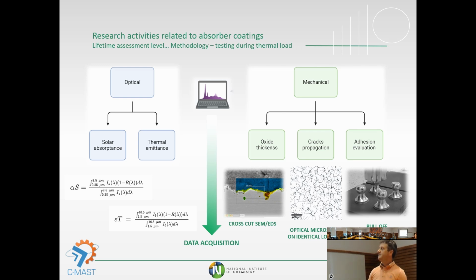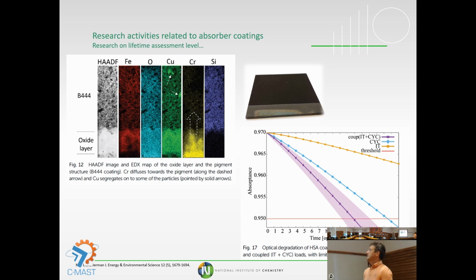In the meantime, we test weekly the solar absorptance, thermal emittance, and also mechanical properties like thickness, cracking, and adhesion evaluation, in order to get a lot of data to produce a good foundation for modeling. As you can see here, we also quite often cut the coatings. We make lamellas out of these coatings after loading, and we evaluate how the chromium is moving inside the coating.